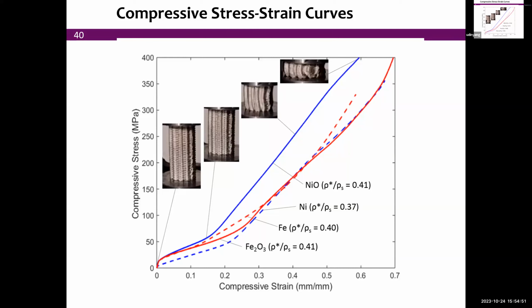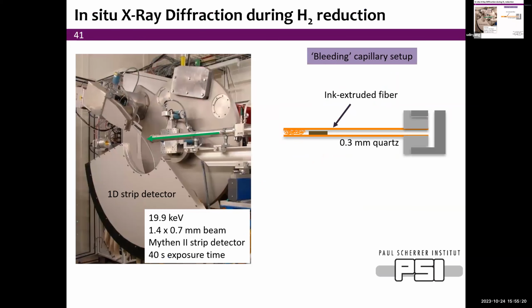So for energy absorption applications, this might be also useful. And it's dependent on the relative density, which is around 40% relative density. Here, this is the macro porosity between the struts and also the inner porosity when present within the struts. And so you see very uniform, and so no instability, no shearing, no fracturing, no spalling that you see in other types of materials that are more brittle.